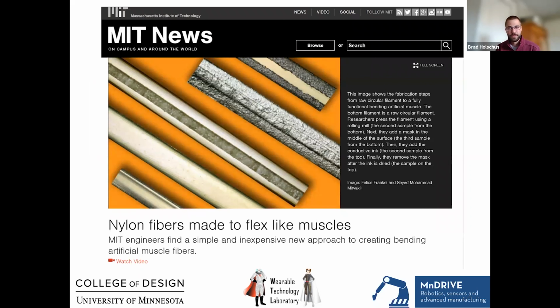Other work in this space, this was a paper put out by MIT a bit more recently, also looking at using nylon, but in a different way than the folks at UT are doing it. Here, the MIT folks take nylon fibers and coat parts of the fibers in a conductive material. So now these are electrically conductive nylon fibers. But what's interesting about it is they don't put the conductive material uniformly across it. They put it across pieces of it and then run a current through it. And then those pieces where the conductive films sit get hotter than the places where the conductive film is absent.